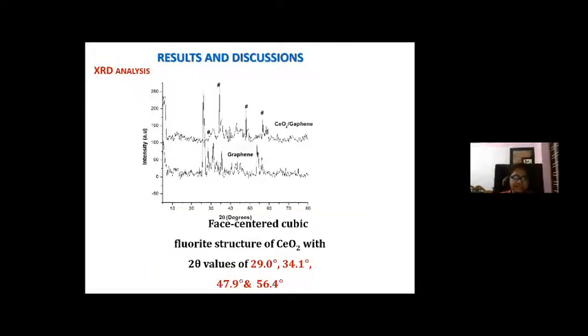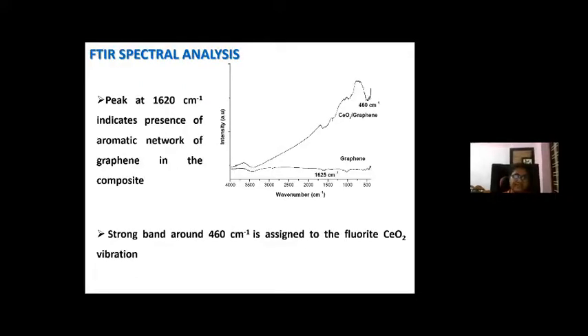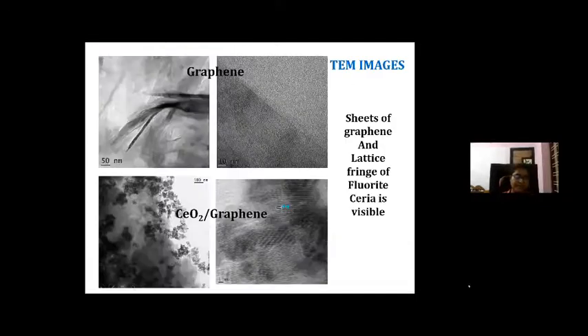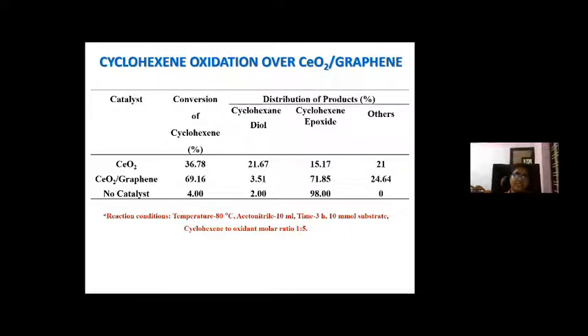About the material characterization, this is the X-ray diffraction pattern of ceria graphene, and it indicates the formation of a fluorite structure of ceria over graphene sheets. The FTIR analysis indicates aromatic carbon-carbon double bond vibration, and also the fluorite ceria vibration at 460 cm^-1. From the TEM analysis, we can see the sheets of graphene and also well-distributed ceria particles on the graphene sheets. The fluorite ceria lattice fringe at around 0.32 nanometer, corresponding to the 111 plane of ceria, is also visible from the TEM images.